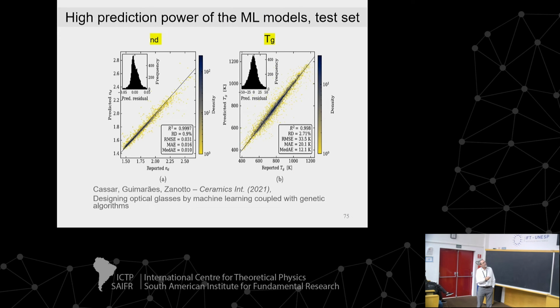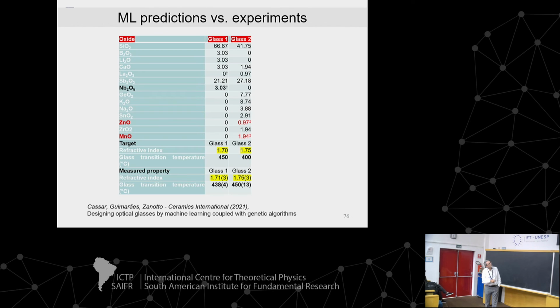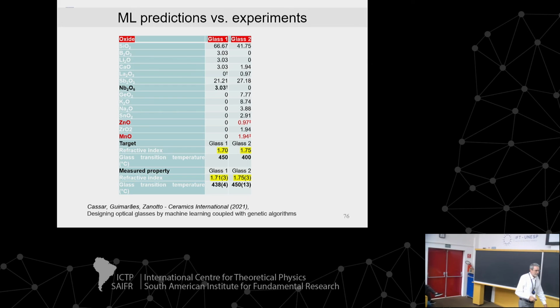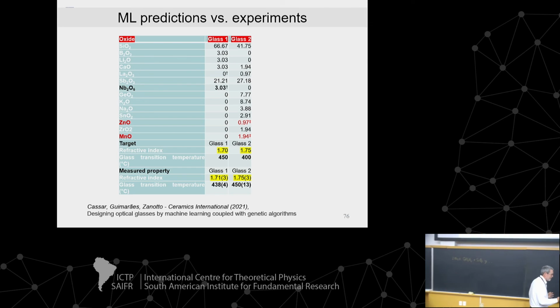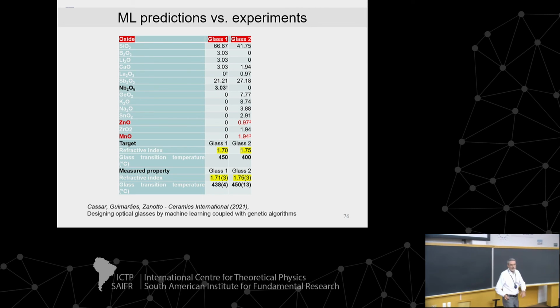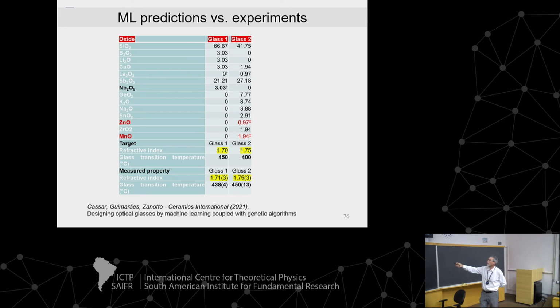Here's the training and the result of the training. Predicted value, reported value. Predicted value for TG, reported value for refractive index, for TG. And that's it. The algorithm. Nobody made this glass. This particular algorithm said, hey, you want a glass with 1.7 target and a TG of 450, so try this composition here.